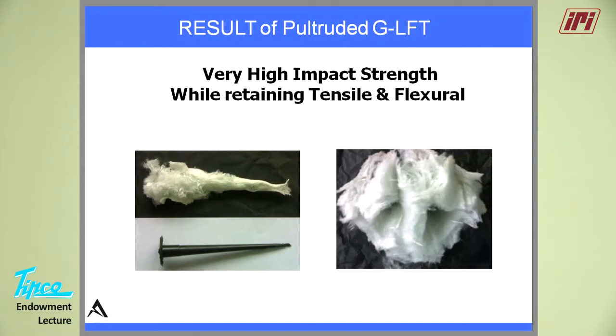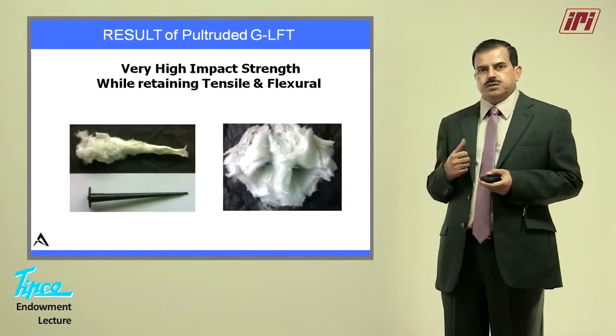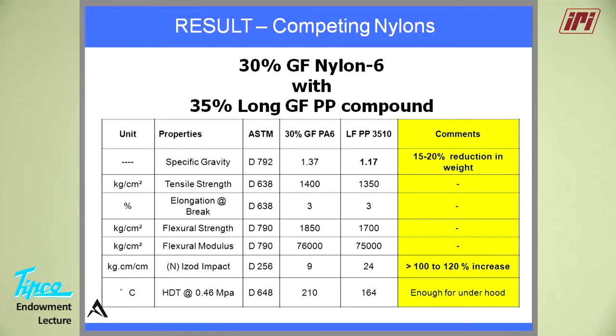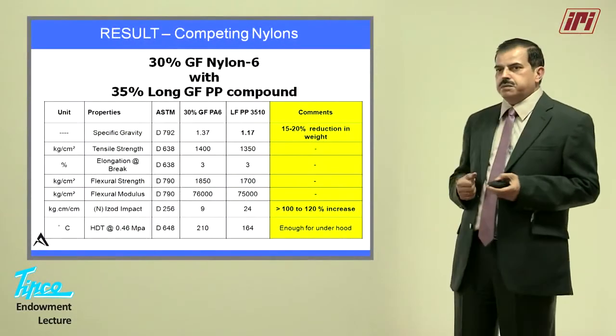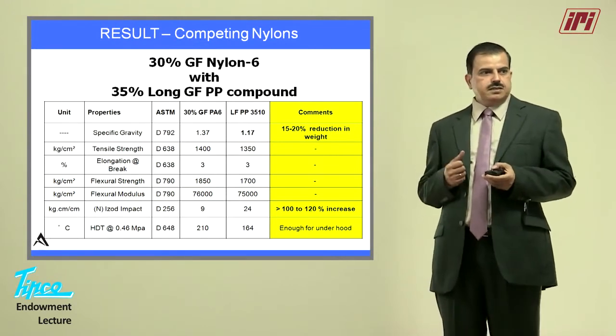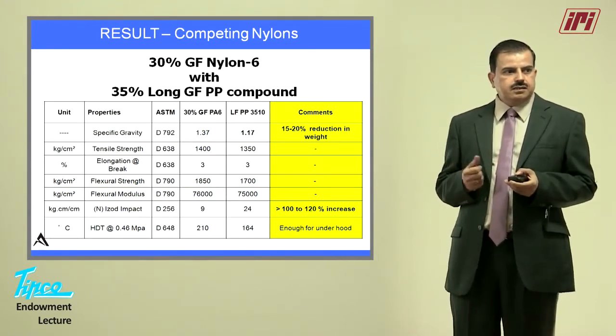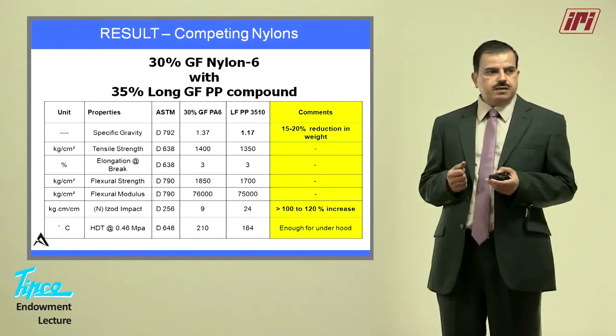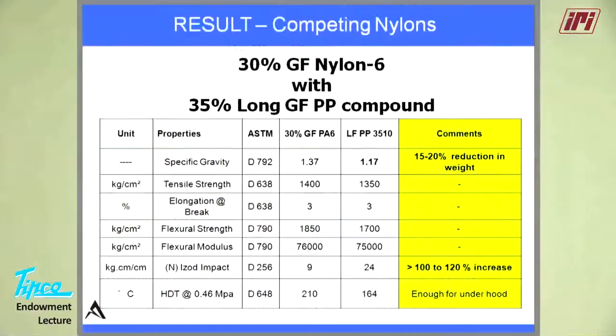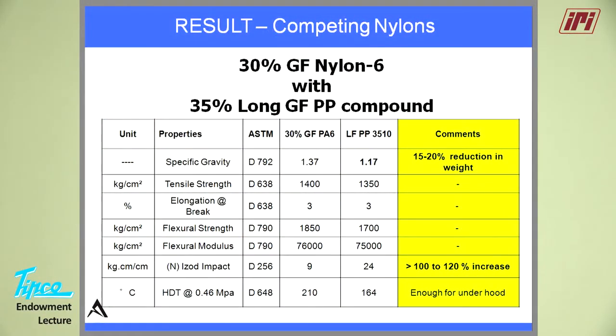By doing this, you are using a very efficient process of injection molding, and you are trying to reach towards the properties of FRP. You can see some comparisons I have shown here: a 30% glass filled nylon 6 can be replaced with 35% long glass fiber PP compound, and this gives enormous benefits of approximately 17% reduction in the weight of the part, approximately almost double the impact strength of 30% glass filled nylon 6. Very similar properties of flexural strength, so you don't have to change the thicknesses.